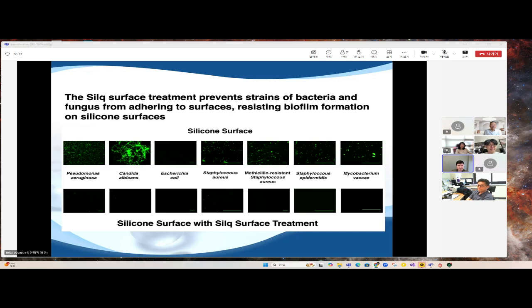So this is some initial data that we produced. We applied the treatment, the zwitterionic or the Silq surface treatment, to silicone devices, little discs. And we incubated those discs, this is just bare silicone, so no treatment, control discs, versus the discs with our surface technology on it. We placed them in the same environment with different types of bacteria, and you can see the adhesion of those cells all over the uncoated silicone. But with the coated silicone, you can see the effect it has at resisting the deposition of those different strains